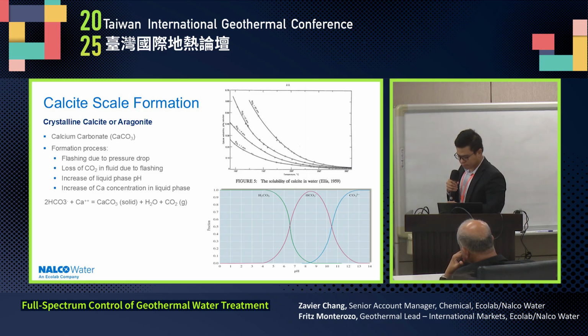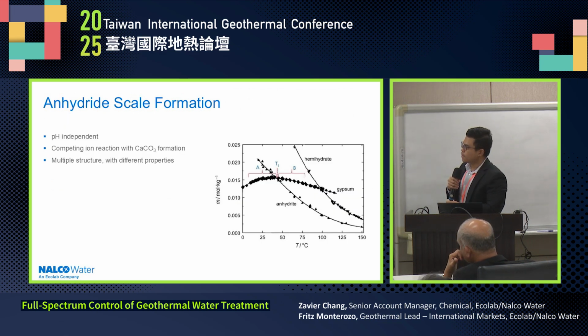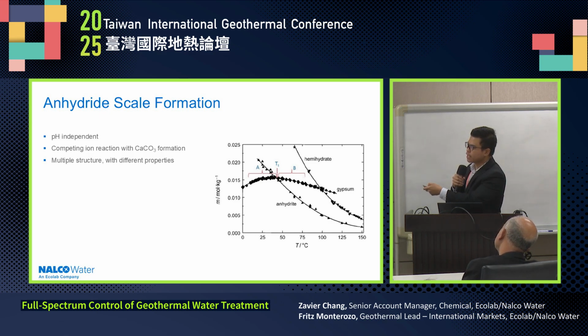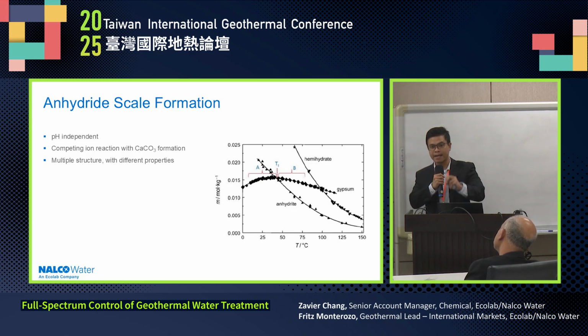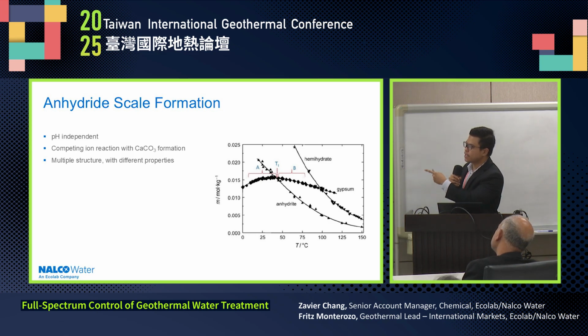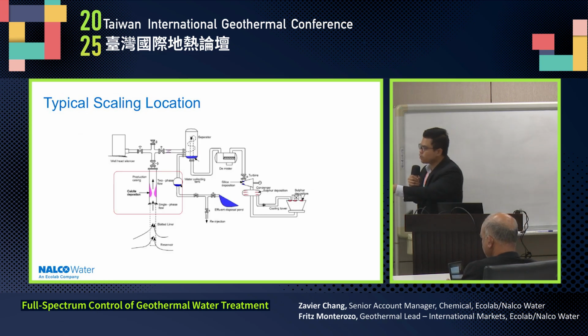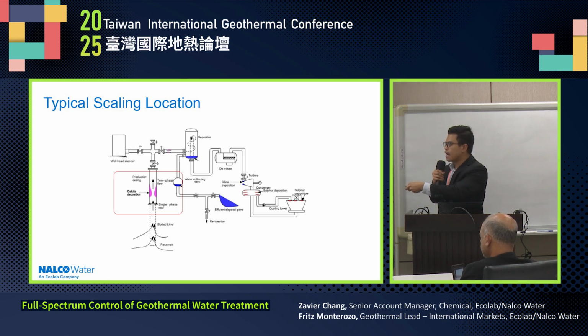That's why anhydrite, which is calcium sulfate, has the same deposition behavior as calcium carbonate, but this one forms in high temperature regions. It is not dependent on pH. So usually you see anhydrite in the deepest portion of your well. So typical scaling location is in your production well, here at the flash point.